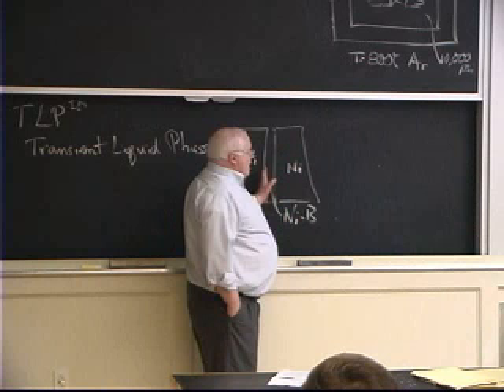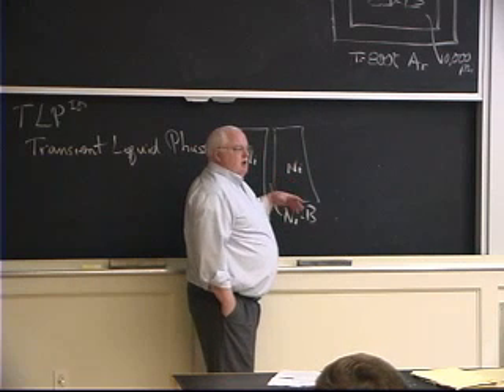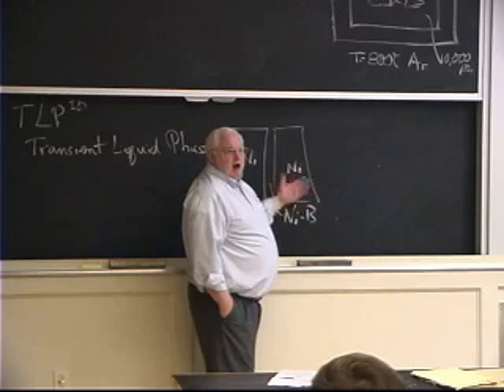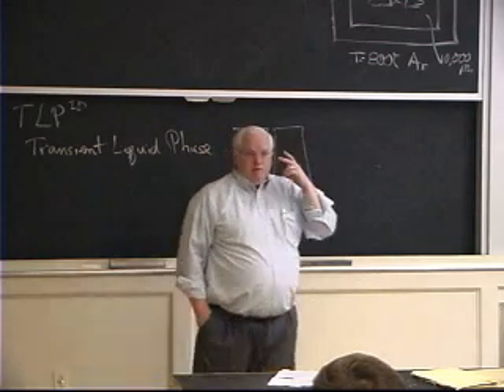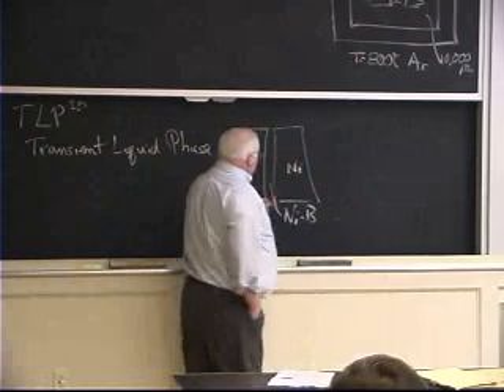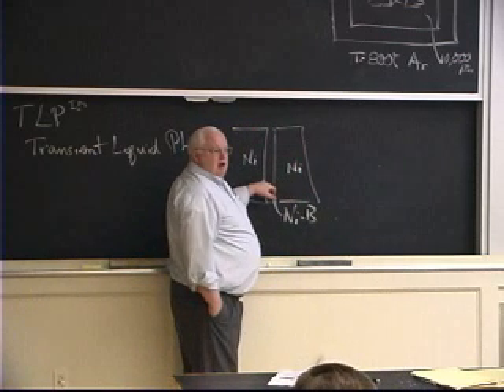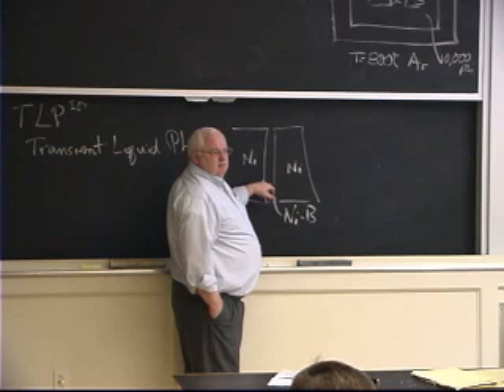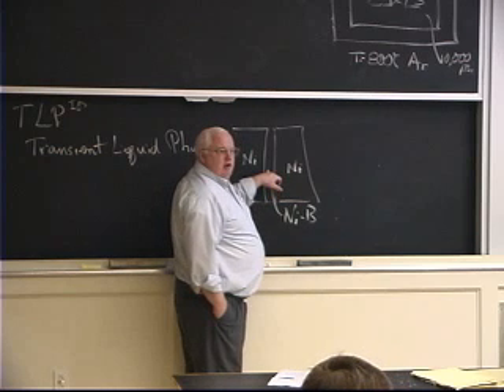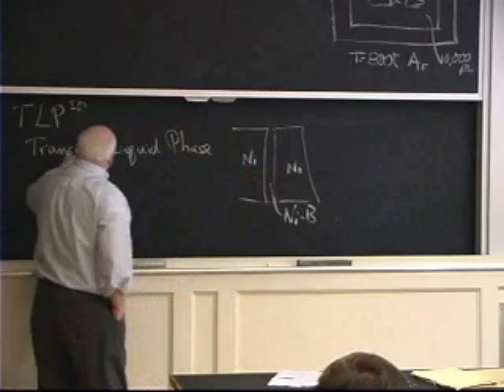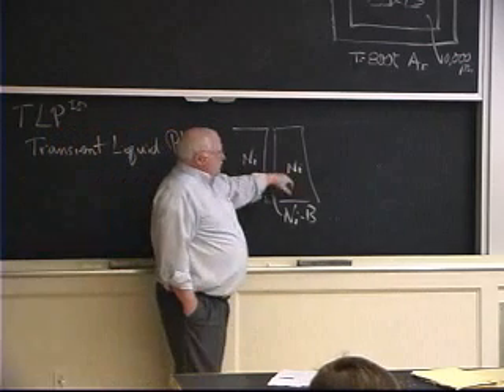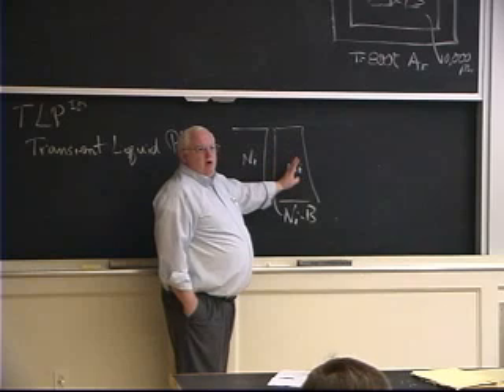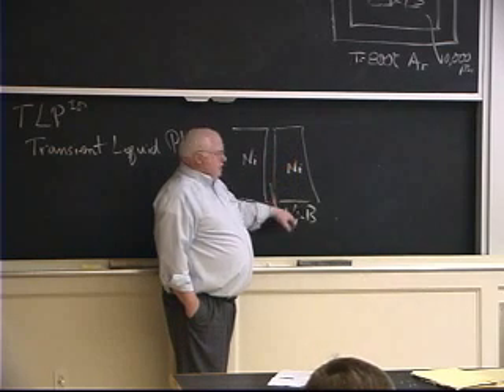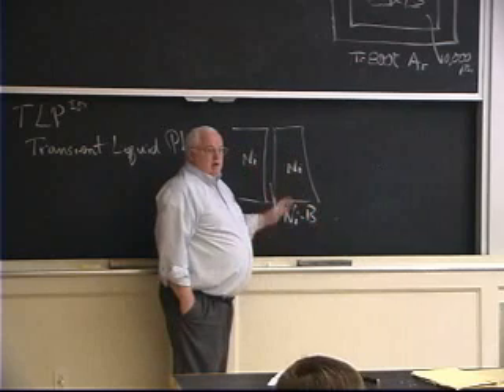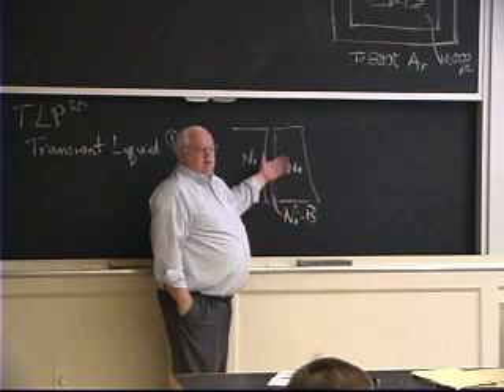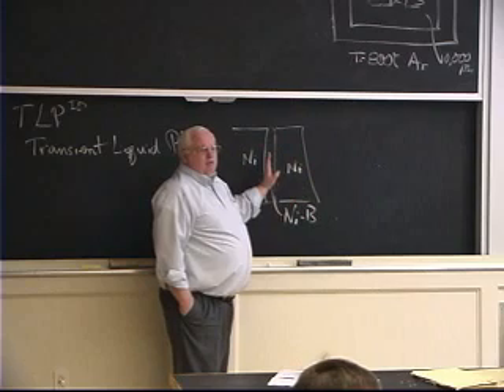And if I hold it at the brazing temperature, not for a couple of minutes while I'm making the braze, but for a couple of hours. And I'm not talking about 24 hours like a typical diffusion bond. I'm talking about maybe 2 hours. I can diffuse the boron away and leave behind relatively pure nickel here. And I essentially raise the melting point of my liquid. So it's a transient liquid phase. I heat it up to the point where I get a liquid between my two solids, but I diffuse away what we call the melting point depressant. Okay? In this case, the melting point depressant is boron. And if I diffuse it away to the base material, I will raise the temperature, and I end up with something that's called isothermal solidification.